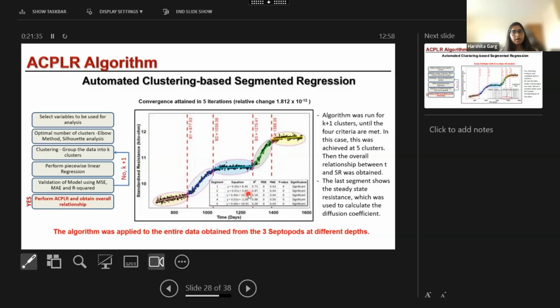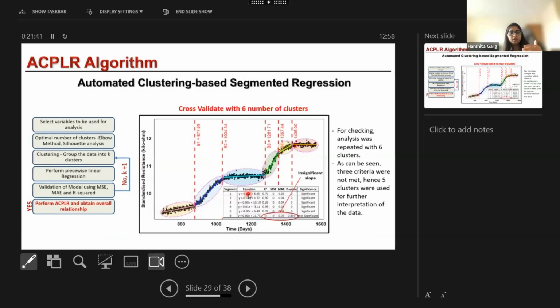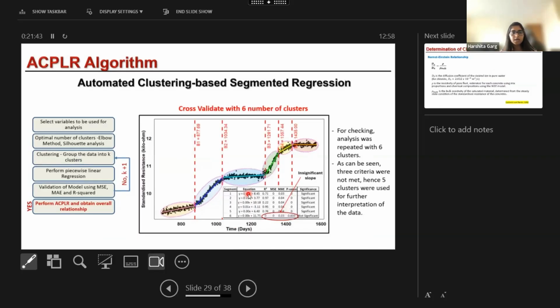Now, this algorithm also reinitializes to cross-validate with the increased number of clusters. So instead of 5, it goes up to 6 and cross-validates and checks if all the criteria are again met or not. In this case, as we can see, it doesn't meet all criteria for 6 clusters. That means the optimal number of clusters was 5.